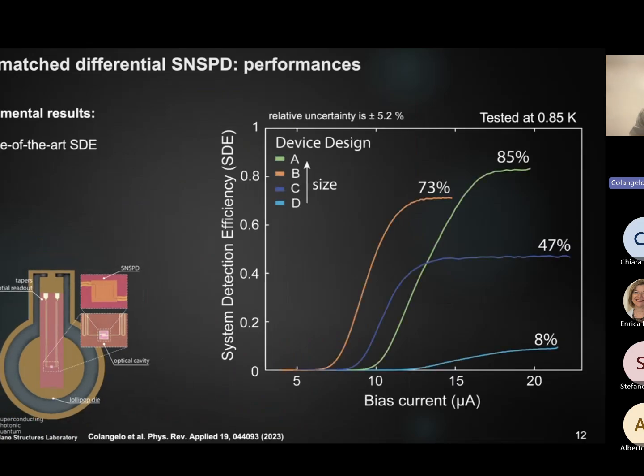So when we test this device, we made a few actually. This is a standard way to characterize the efficiency. You typically plot it as a function of the bias current. Here we test 4 devices from the smallest to the largest, D to A, and we can see that the efficiency increases from 8% to 85% following the area. This makes sense because a larger detector gives a larger efficiency, and our maximum efficiency is actually 85% due to some small issues with the optical design, but nothing intrinsic to the detector really.